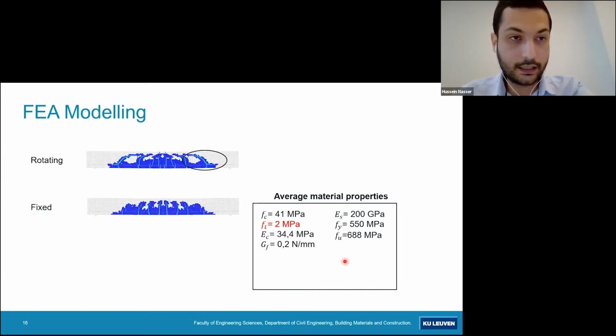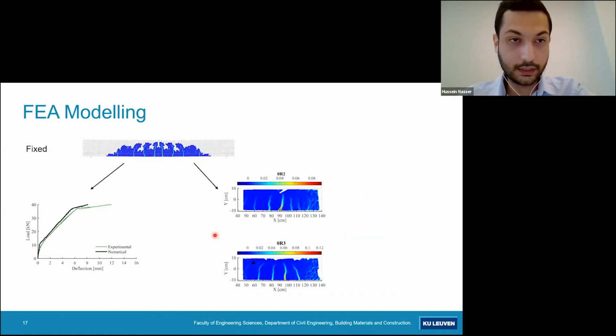As for the cracking model, I noticed that if I use a rotating crack model, the model would predict the formation of a shear crack, which was not observed in the experimental test, while a fixed crack model shows a more stable behavior of the cracking. I explained this by the fact that a fixed crack model includes a shear retention factor, which plays the role of aggregate interlock and can actually stabilize the formation of shear cracks, especially if those beams have no stirrups. So after introducing the model and the different material properties and the cracking models used, it can be seen that a good validation has been obtained.